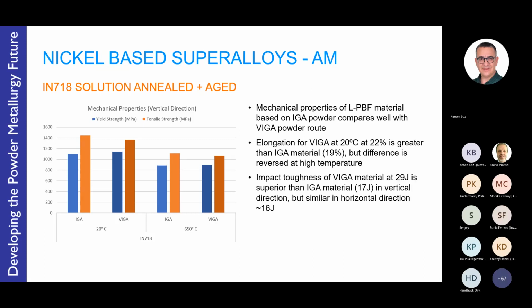Mechanical properties, elongation, and ultimately the vacuum inert gas atomized powders are found to be slightly superior in terms of elongation and in toughness. And no doubt when it comes to fatigue and creep performance, the lower levels of non-metallic inclusions in the vacuum inert gas atomized powder will be highlighted in these types of dynamic test criteria and will show superior properties compared to inert gas atomized powders alone. However, it does depend on the application.